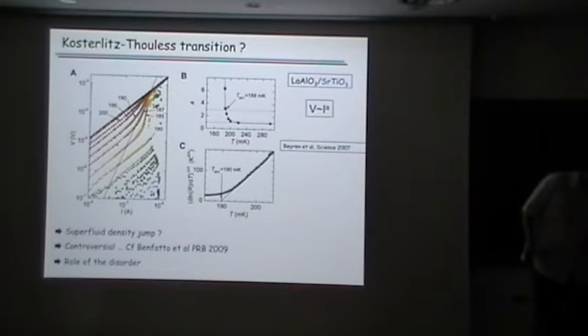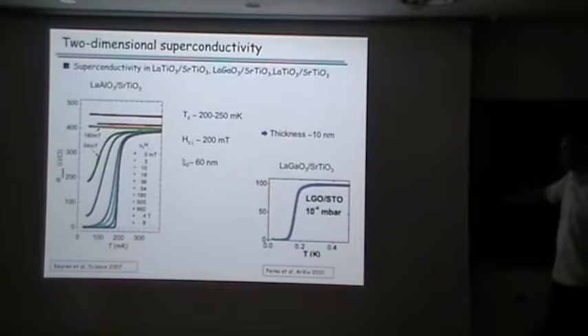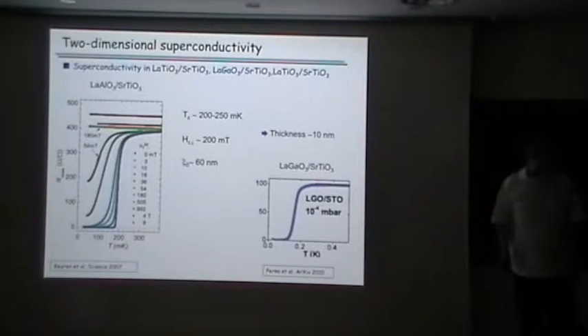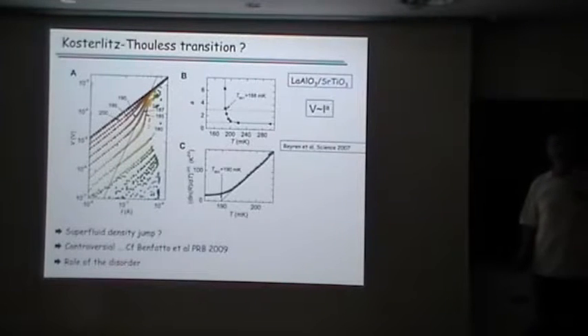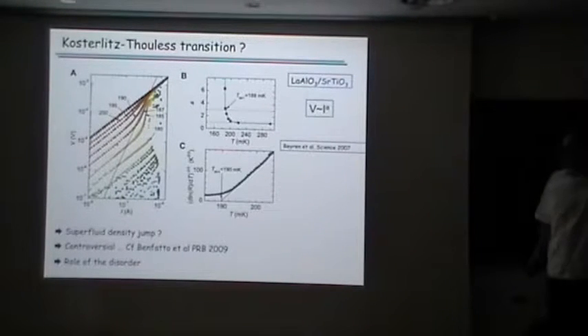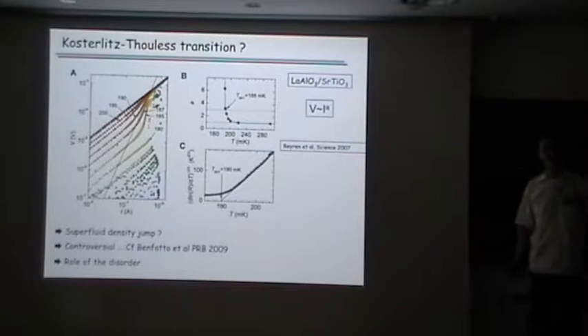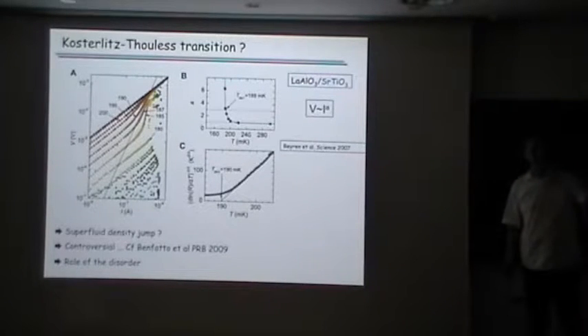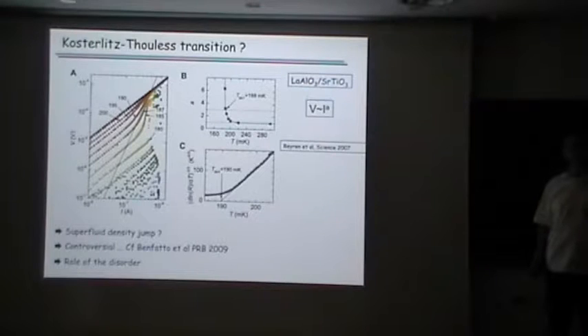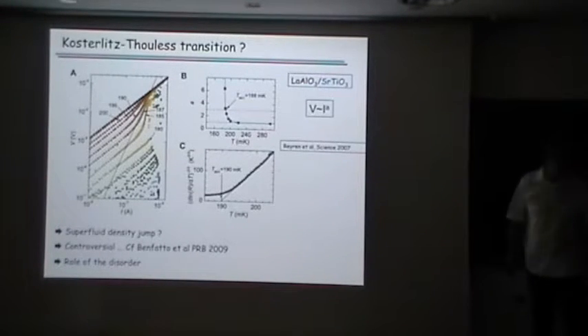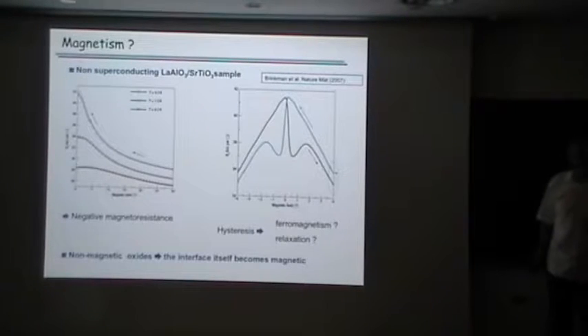And of course, you see the TC is not that sharp, especially here, and therefore it's difficult to define the mean field TC, and if you don't know where the mean field TC is, it's difficult to get the distance to the Kosterlitz-Thouless transition. So I think this is potentially a very interesting system because it's a 2D system, and as you will see in a moment, you can change the superfluid density. So for the first time, you can easily change the superfluid density in a charged superfluid and see the Kosterlitz-Thouless transition in detail. But I'm not sure we are in this system already at this point.